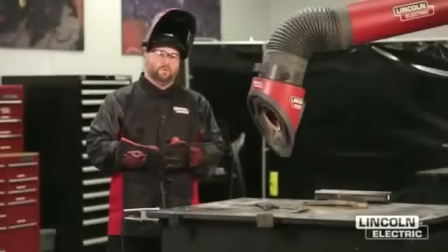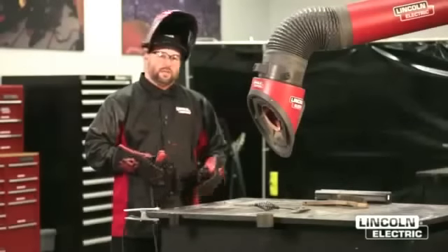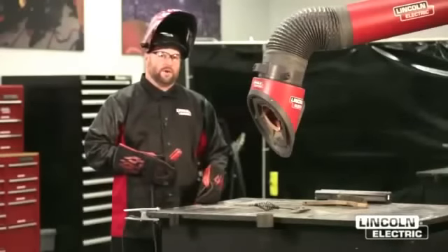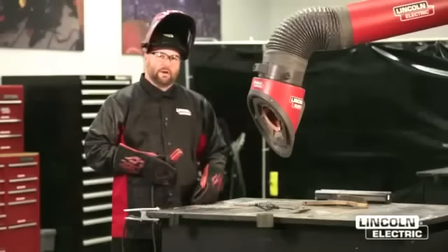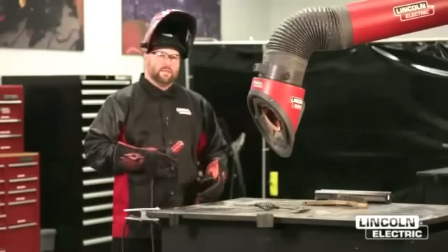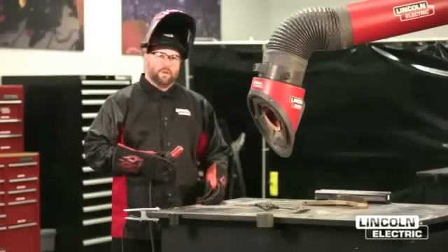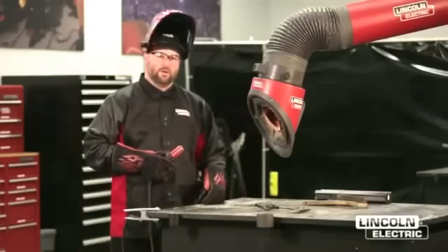We've made a weld with our 6013 at the low end of the setting. We were at 90 amps, and we can see that our weld was very convex, very little penetration in our base material, and a very narrow looking weld.